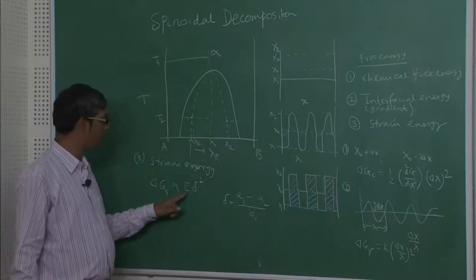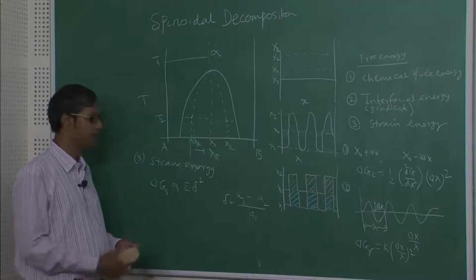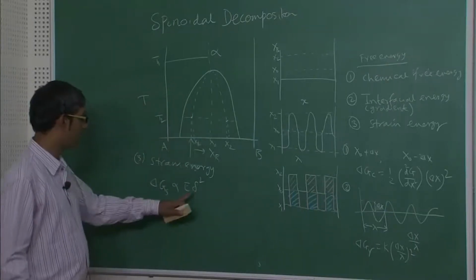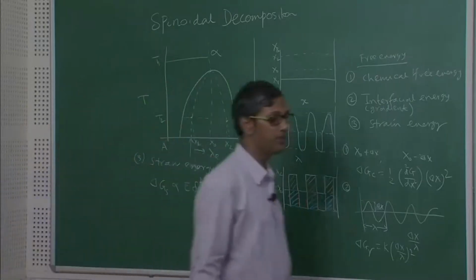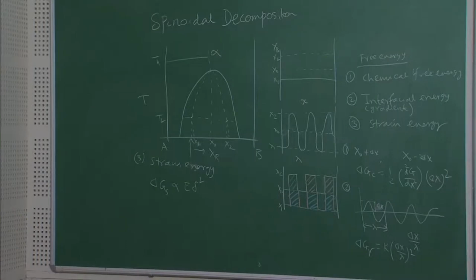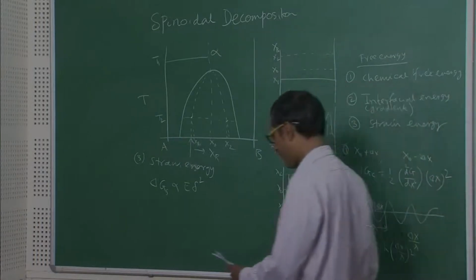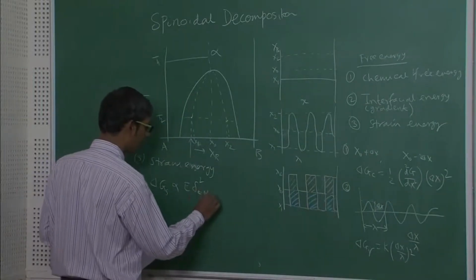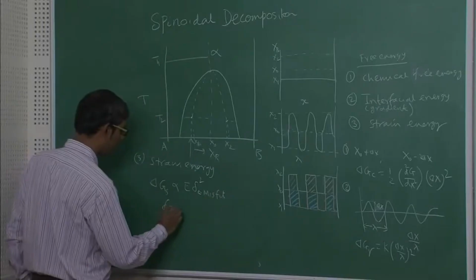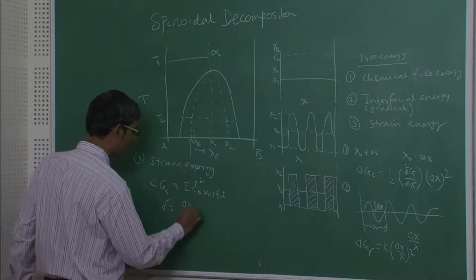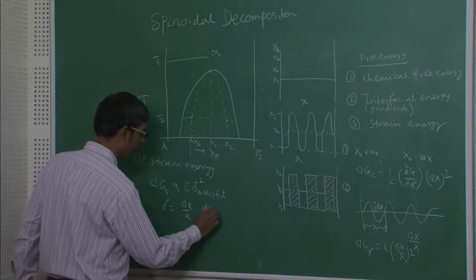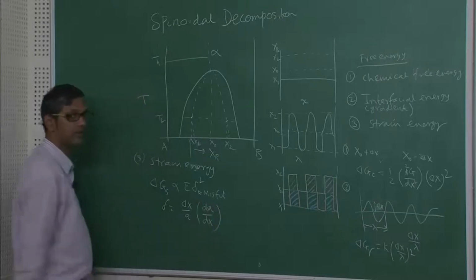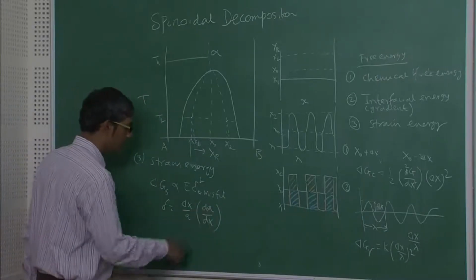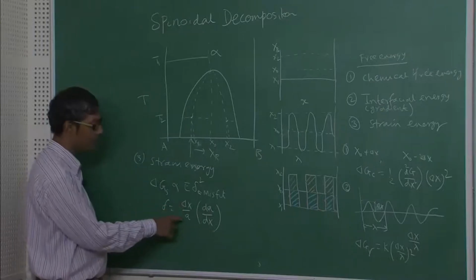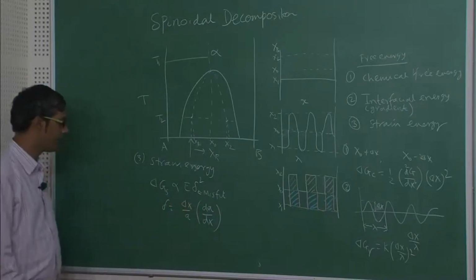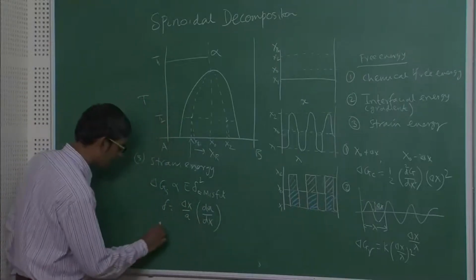Now if I know the misfit and if I know the elastic constant, then we can calculate the Gs. Obviously the delta depends on the compositional variations. Basically delta can be written like this: delta x by A multiplied by dA by dx, where A is the lattice constant of the random solution, okay. So if I have a compositional difference of delta x and lattice parameter A, this multiplied by this derivative will give you basically delta. Now we can actually write down delta Gs in a much simpler way.